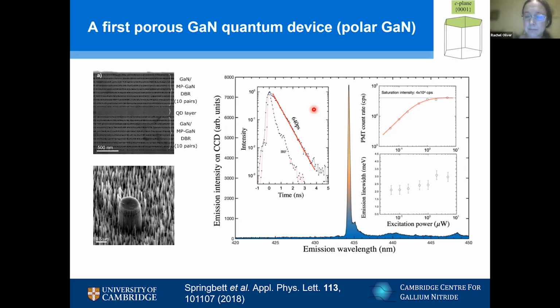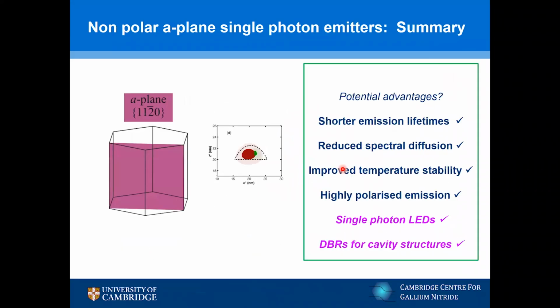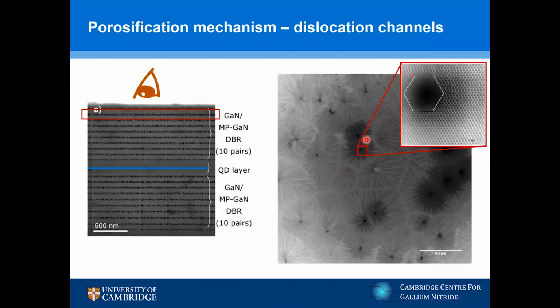No problem. In your STEM image, it looked like the image was fading as you moved into the defect. Is that because we're looking into the defect? Yeah, so I think the thing we have to be a little bit careful of here is that we did have to make the TEM specimen. So some of what's going on here is the impact of making the TEM specimen on how the material ends up in the foil. You can see, particularly over here in this region, we've got this region which is all looking very dark. I don't think that's how the material is.